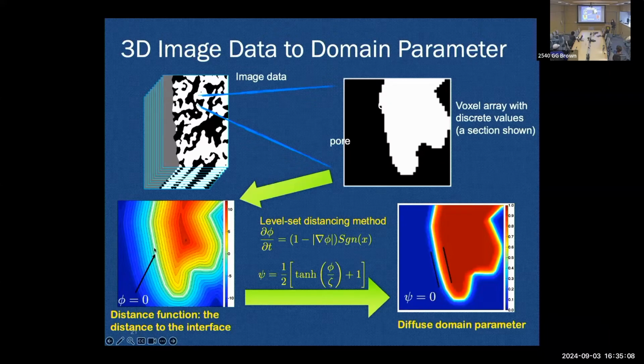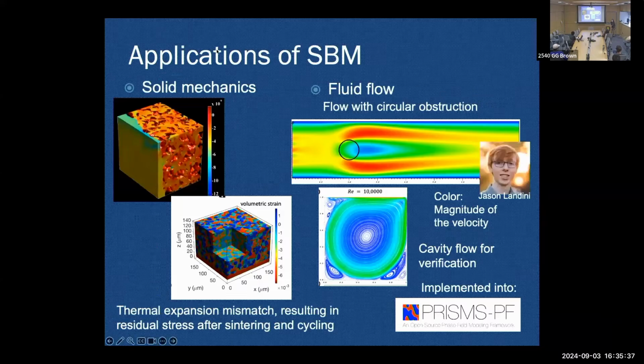And then as you go away from it, it's the distance to the closest interface, the closest boundary. Once you have that, you stick it into the hyperbolic tangent equation, and you get this nice diffuse interface description of the microstructure, which can be used with the smooth boundary method. So you can use this to solve the solid mechanics equation.